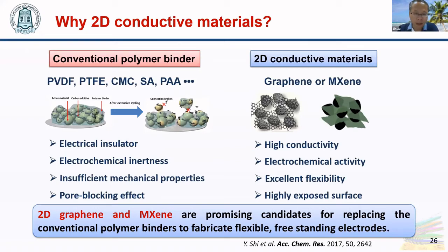The usage of polymer binder has some shortcomings. These materials are electrical insulators, so it is adverse to the energy and power density of the devices. And also polymer binders are electrochemically inert. Usually they will occupy 5 to 20% weight, but cannot provide any capacitance.